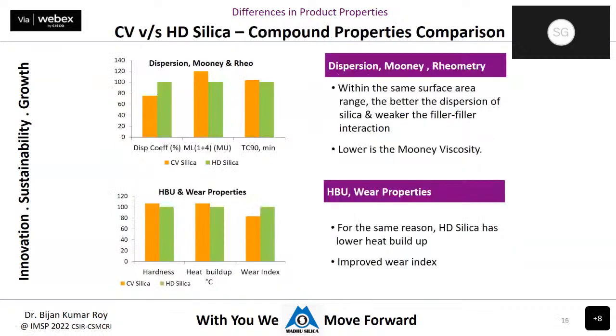Now I will just show you 2-3 slides. It is a comparison between the regular silica and the highly dispersible silica. If you look at the compound properties, the end product properties, dispersion is better. Mooney viscosity actually dictates how we process the compound. So the lower the Mooney viscosity, the better it is processed. With the highly dispersible silica, it always gives a lower Mooney viscosity. In terms of curing, that is in terms of production, highly dispersible silica and regular silica are comparable. But from the processing point of view, the dispersion point of view, and ultimately the product mechanical properties like heat buildup or wear properties are always better with highly dispersible silica.